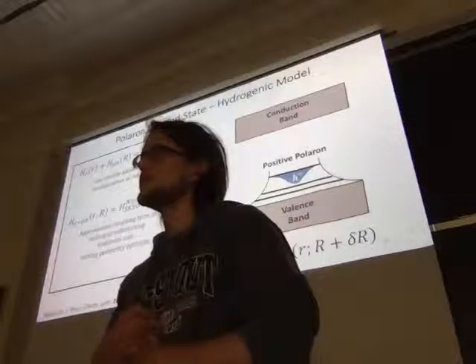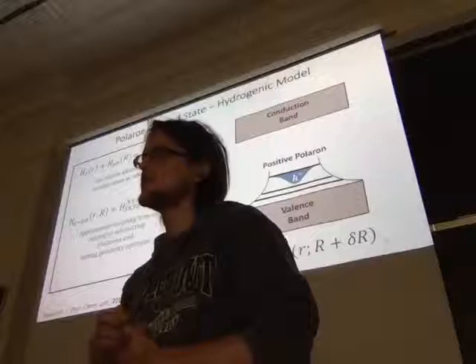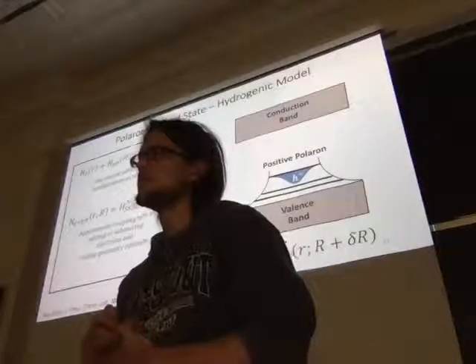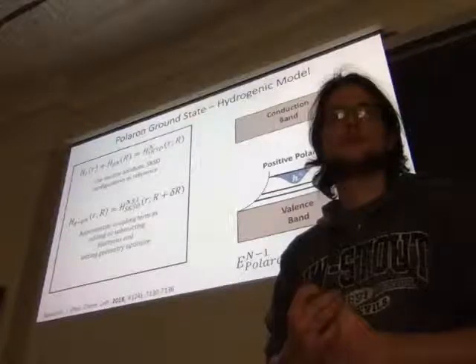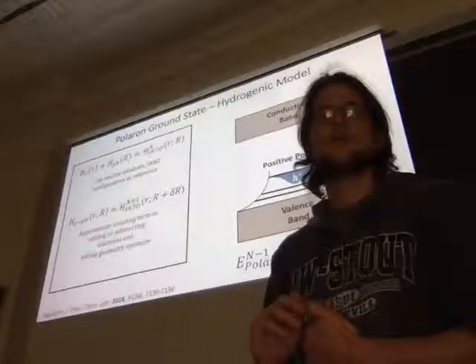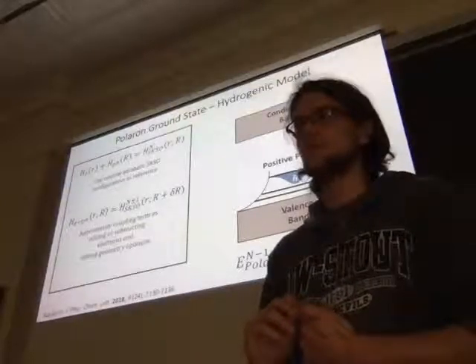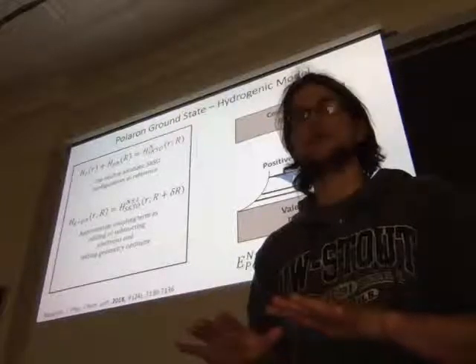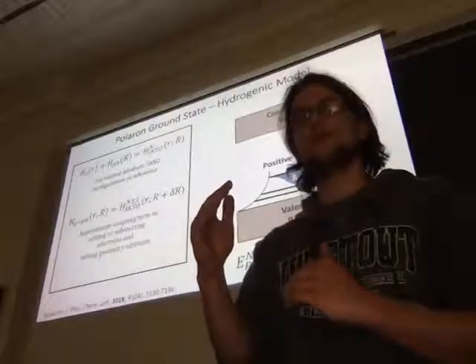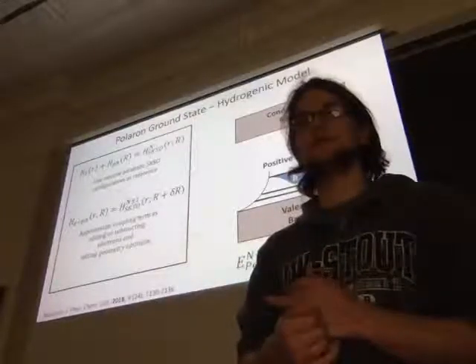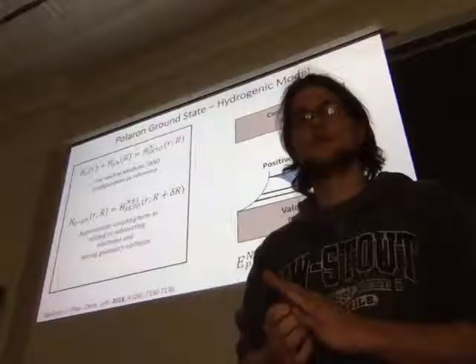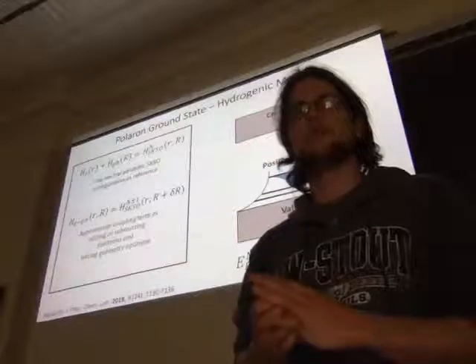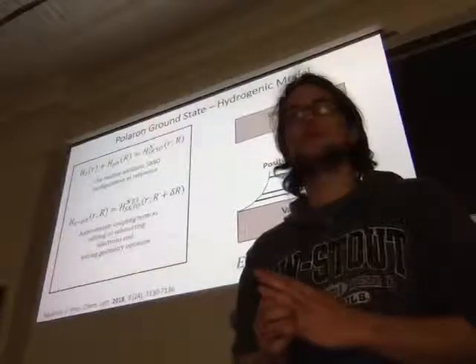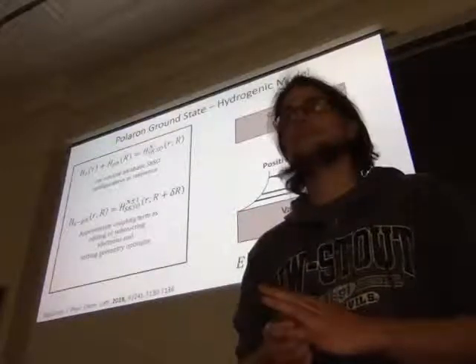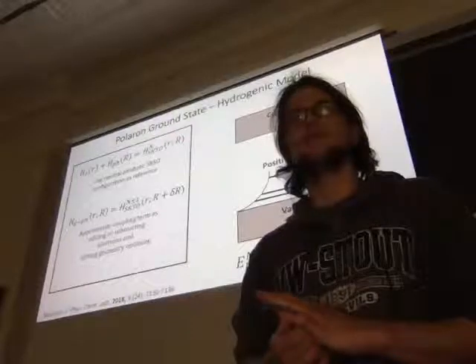And getting dressed. So in the case of a nanocrystal, you have something that you can follow. Do you also have that in the case of a bulk crystal? Yeah, but the polaron is just intrinsic to the polar crystal structure itself. So no matter what dimensionality, in some sense you would expect a possibility to see polaron formation. I guess it hasn't been experimentally shown in perovskite nanocrystals yet, but there's some evidence, at least to me, that it seems useful to think that there are polaron occupations there.